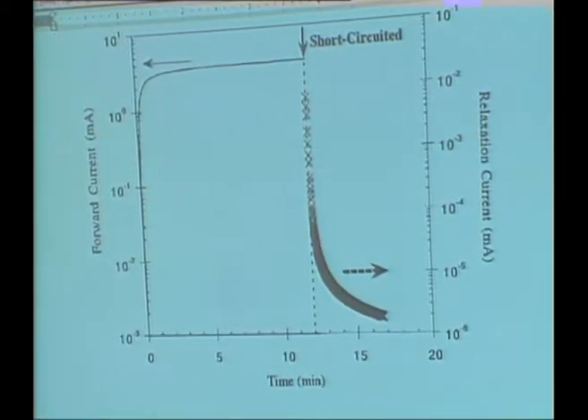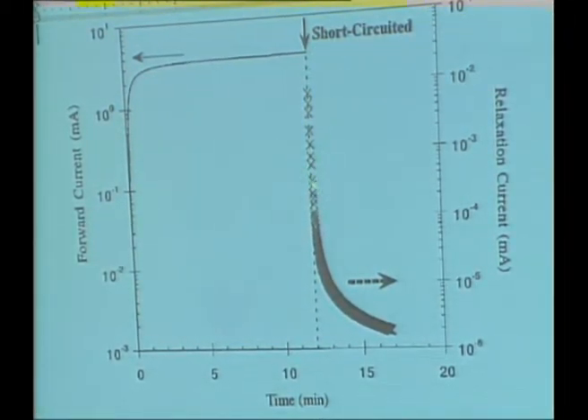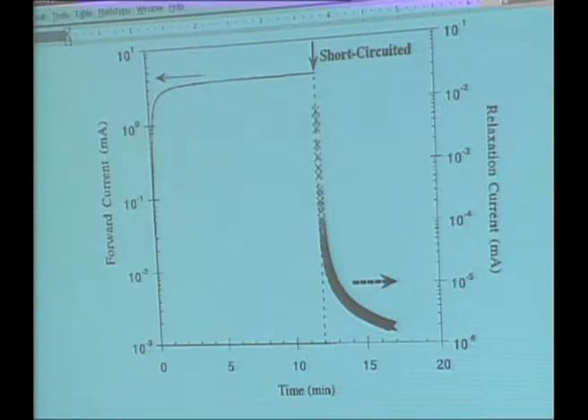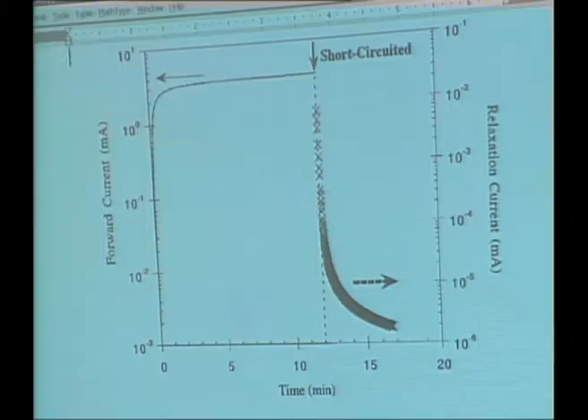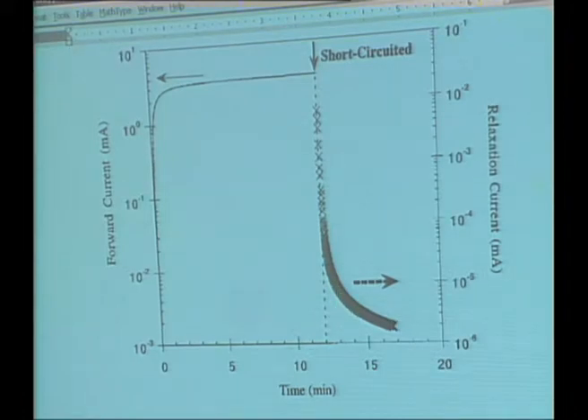So here's what was done here. We charged up that little cell, and then we shorted it and measured the current, and sure enough, one does see current flowing through the external circuit. There's a lot of current flowing through the internal material as well, which I'm not measuring here, but this is at least proving that I made a battery because I stored the charge and it came out. And although the time scale is not very long, it is pretty long. It's whatever here, 3 minutes. It's not an RC time, not a capacitor. That's real discharging of a battery because it happens over a period of a few minutes.